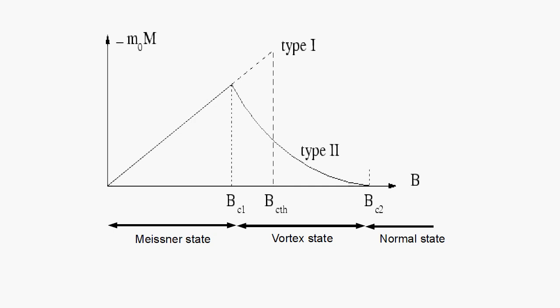Here's the magnetization curves for type 1 and type 2 and what they look like. As you increase the field along here, that's the applied field, then you'll get an equal and opposite magnetic field induced in the material. For type 1, there's a sudden critical field at which it suddenly becomes non-superconducting. With type 2, there's a lower critical field at which these flux channels start to form inside the material. And gradually, as you increase the field strength, more and more of the material gets occupied by these flux channels until the entire thing resorts to being in the normal state at some upper critical value.